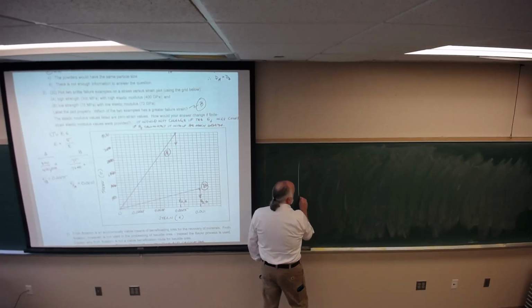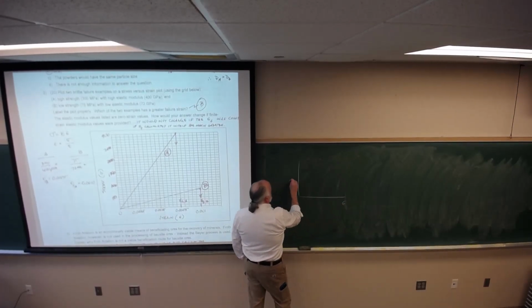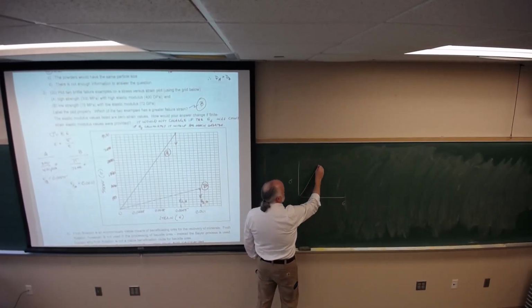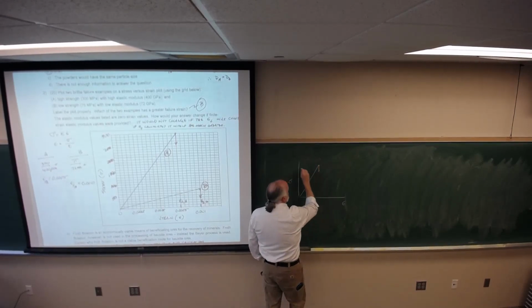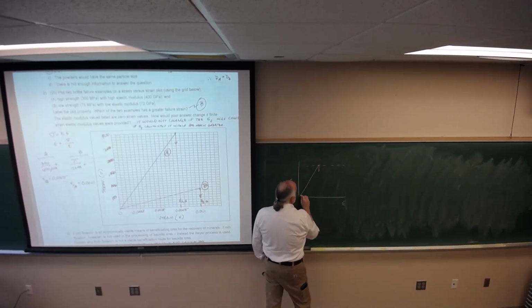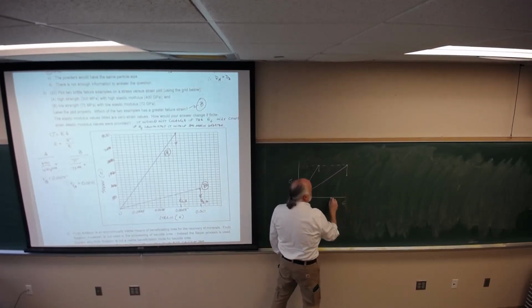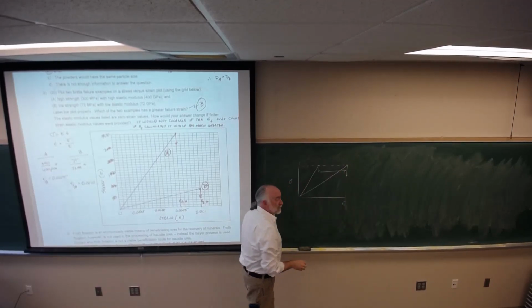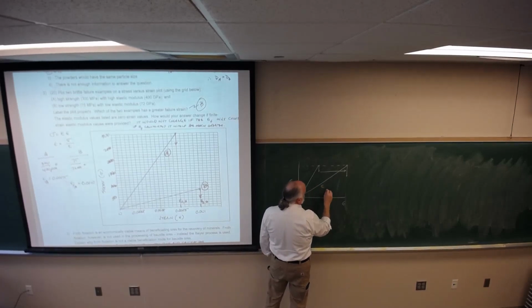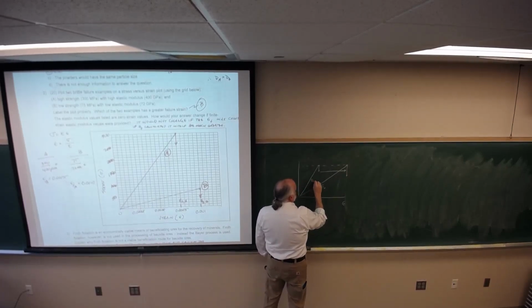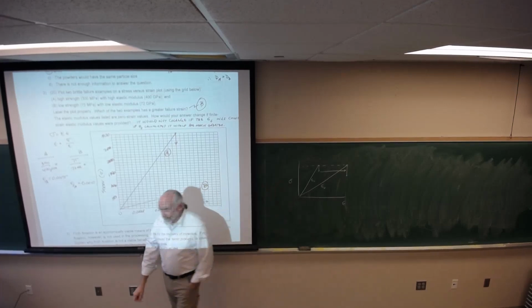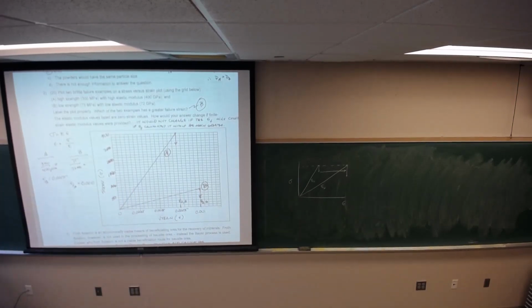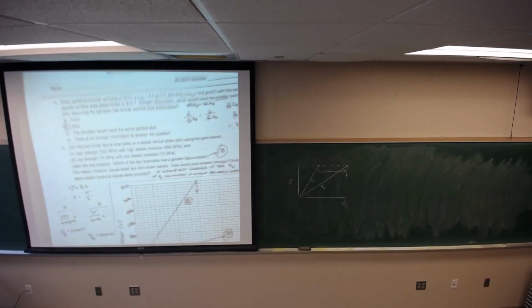So you would have this strain versus stress, and here's our first case, right, for failure. But our stress level stays the same. So if I reduce my elastic modulus, my strain at failure increases dramatically. So this is elastic modulus finite versus elastic modulus from zero strain. Good? I'm pretty lenient on that one, and your opportunity, of course, is to argue for points if you don't like what I said.